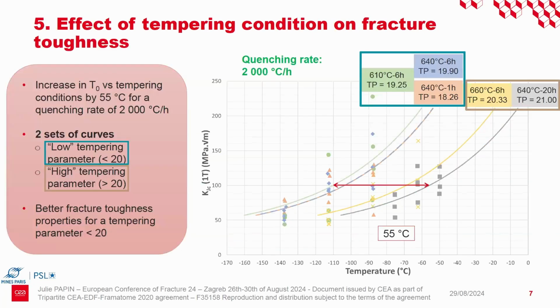Now, if we look for a given quenching rate of 2000 degrees per hour, and we compare the tempering conditions, we can note that T0 increases by 55 degrees for this quenching rate. And the important thing is that we have two sets of curves, one of low tempering parameter under 20, and a set of curves of high tempering parameter over 20. And we can note that we have better fracture toughness properties for tempering parameter under 20, around 90.